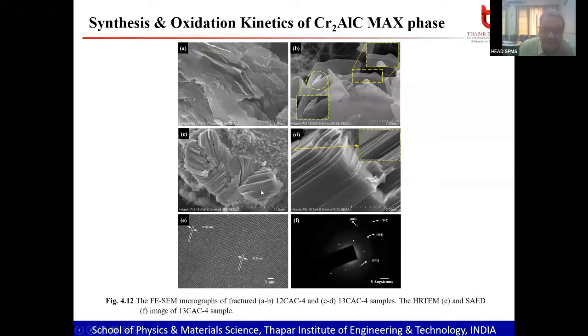So if you look here, the orientation of different planes becomes important. You can see that this is one type, here one type, here one type. But every part is just like a layered structure. And because we have used the fracture surface, the flexibility can be determined. If you look here in detail, this is the bending. This bending phenomenon, B part in the microstructure, which I have shown over here in the inset, you can see this B part is flexible in nature.